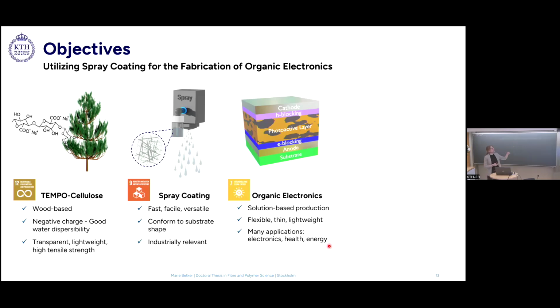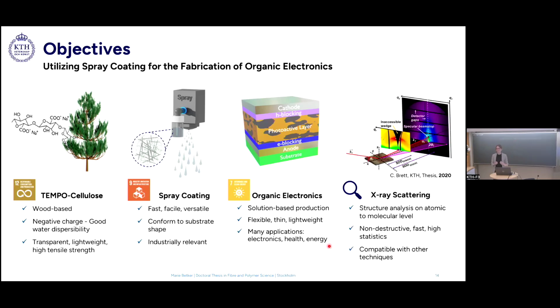And as you can see in this model, these organic electronics consist of layers, or these are multi-layer systems. And this means I had to use surface-sensitive techniques, so AFM, SEM, sheet resistance measurements, and importantly, the X-ray scattering. Because with X-rays, we can probe our samples down to the nano and angstrom scale to actually understand the structure of our materials. But on the other hand, it's also a non-destructive technique, very fast. And if you work under a grazing incidence, you can get very high statistics. And you can also combine this X-ray scattering technique with other techniques, such as a heater, for example. You can heat your sample during the measurements, or of course, you can combine it with a spray nozzle.